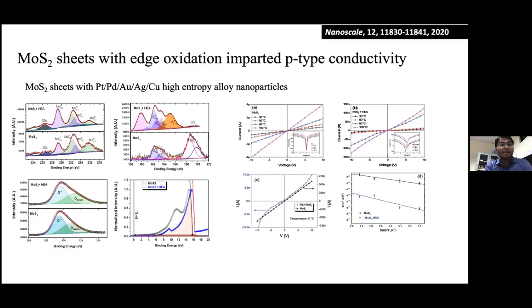You can see from the IV, the IV for the bare MoS2 without any particle was linear, and the other one was non-linear. So the linearity or the non-linearity basically quantifies the nature of the contact, whether it is ohmic or Schottky. The Schottky contact is something which is not a bidirectional contact. It is characterized by an energy barrier between the metal and the semiconductor, and the electrons can come in from semiconductor to metal, but from metal to semiconductor side it encounters a barrier and it is not possible.